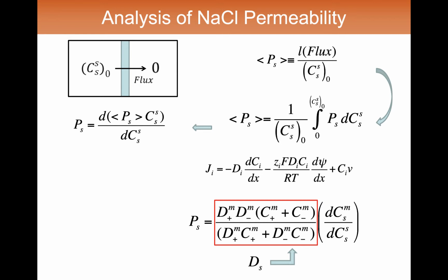And what happens is if you have an ion that diffuses faster than another, say the cation is diffusing faster than the anion, then the cation will get a little ahead of the anion, and that charge separation will set up an electric field that acts to retard the cation transport and accelerate the anion transport. And so overall, at steady state, the ions are drifting through the membrane at effectively a constant diffusion coefficient.